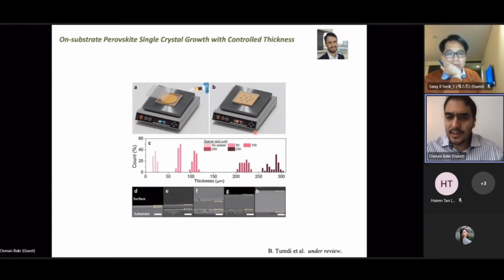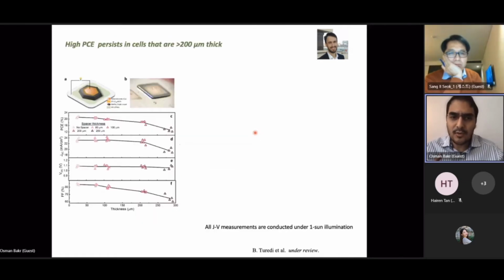And so what we did was we started growing single crystal devices of different thicknesses, starting from 20 microns, all the way to 300 microns. And we wanted to see what happens to the different characteristics of the device. So what happens to the short circuit current? What happens to the VOC? What happens to the fill factor? And in fact, what surprised us is, actually you could make a device that's relatively efficient, even though it's a few hundred microns thick.